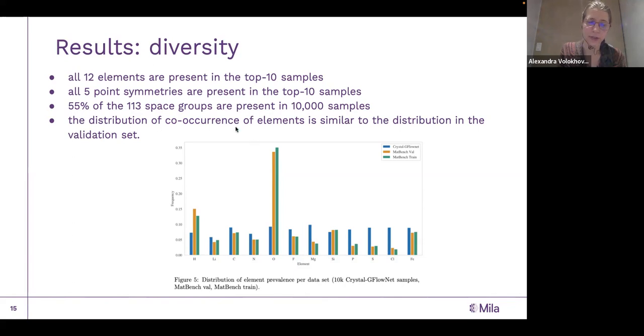We also looked at the distributions of the co-occurrences of the elements, and for the GFN sampled set, this distribution is similar to the distribution in the validation set, and the same is true for the distribution of the elements themselves. We see that GFN can sample all the elements present in the validation dataset, and as I said, these distributions should not coincide, so we do not expect that. But it makes sense that they kind of correspond to each other.